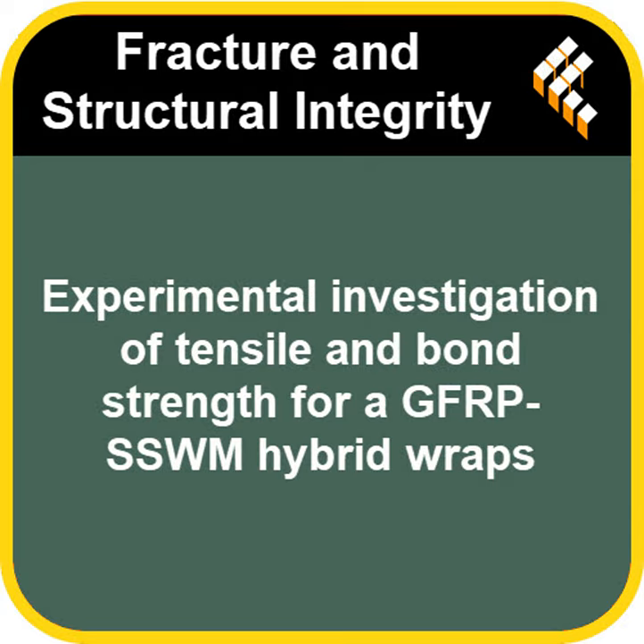And did the way these bond samples failed also tell a story? Yes. The failure modes were revealing. Sometimes you saw the SSWM itself tearing. Which is good, right? It means the bond held. Ideally, yes. It means the material reached its limit. But with GFRP involved, especially if the bond wasn't optimal, you'd see that debonding again, or failure within the concrete layer just beneath the bond line. So the failure mode tells you where the weak link is in the system. Precisely. And the hybrids with Sikadur 30 LP tended to show more desirable failure modes like mesh tearing, suggesting the whole system was working together more effectively.